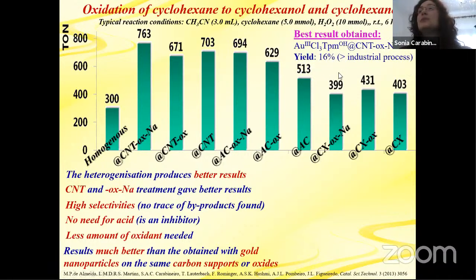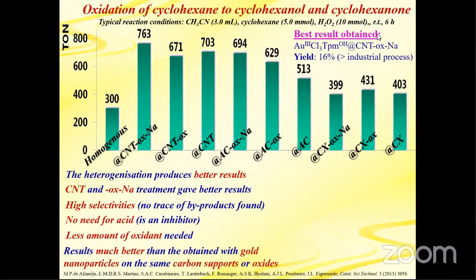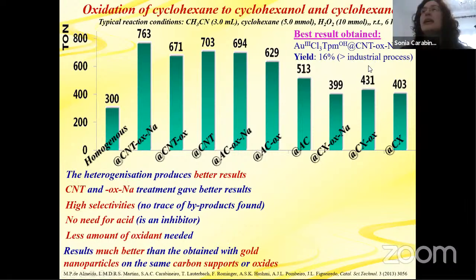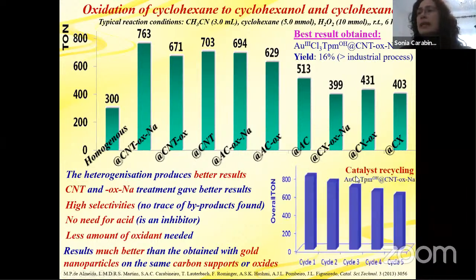So the yield was 16%. Remember that this was only 4%, with higher temperatures, higher amounts of catalyst, etc. And here we did a recycling of the catalyst, and well, some activity was lost, but it could still be recycled. And the homogeneous complex, no, it's only used once and then it goes to the trash.